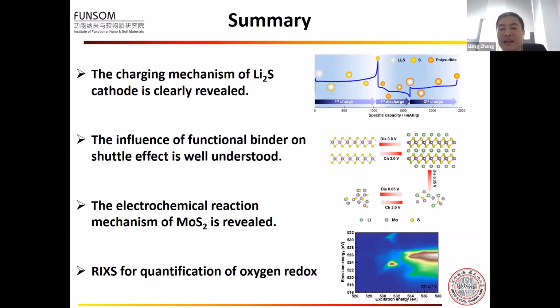If we can, I don't know if the flame mode of sulfur K-edge can be realized, it would be much better. Maybe, for example, if we can take one spectrum on the time scale of seconds, it would be great. The second challenge is the explanation of the sulfur K-edge. Actually, we got quite a lot of sulfur K-edge results, but the question is how to explain the spectral shape change. If we can combine the experiment results with simulation, that would also be very useful. And the third is that for the sulfur K-edge XAS, we can only get the unoccupied states. If we can combine the XAS with XES, then we can get both the conduction band and the valence band electronic structures. I guess we should be able to get more useful information.